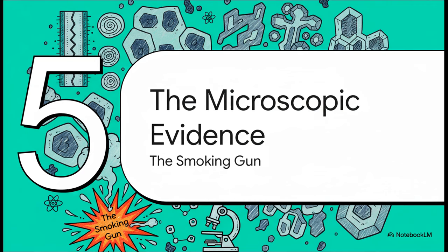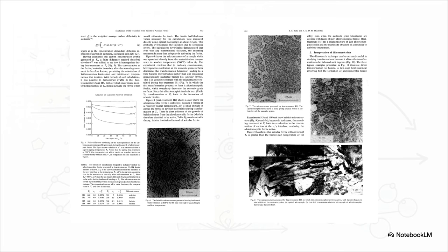And what they saw was the absolute smoking gun they had been looking for. And wow, the results were just undeniable. On the left, that's the sample that was cooled directly. Just like they predicted, the grain boundaries are exposed, and the whole structure is filled with the weaker Bainite. But on the right, that's the sample from the two-step process. You can actually see the thin gatekeeper layer decorating the boundaries, and the inside is just packed with that strong, chaotic mesh of acicular ferrite.